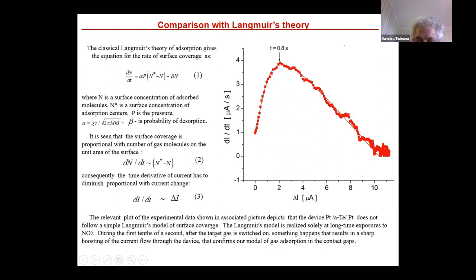does not follow the simple Langmuir's model of surface coverage. In principle, the Langmuir's model is realized only at long time exposure in this range. But during the first tenths of a second after the target gas is switched on, something has happened that results in a sharp boosting of the current flow through the device. That, in principle, confirms our model for surface adsorption in the contact gaps.